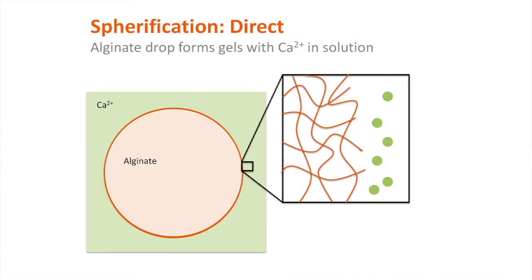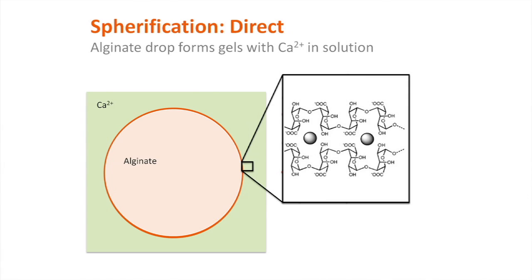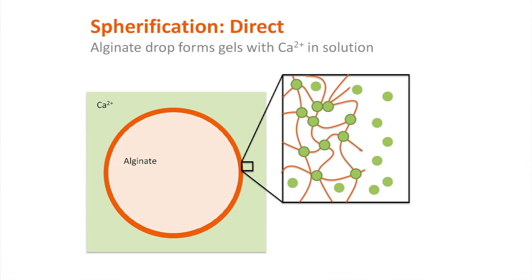What you do is you take the original type of spherification, you take the liquid material that you want to spherify, and you add the alginate to it. Now remember, you can add just something like 1% by weight of alginate, so it's not very much material. You add that, and then the bath that you put it in contains these calcium ions. And the calcium ions flow inside this network and cause it to cross-link. So you get this cross-linked shell, these cross-links, and you form a thin shell, and you can take it out.